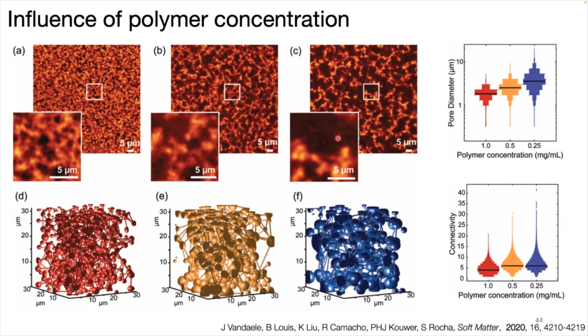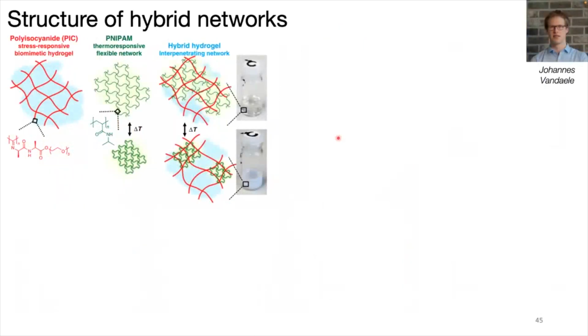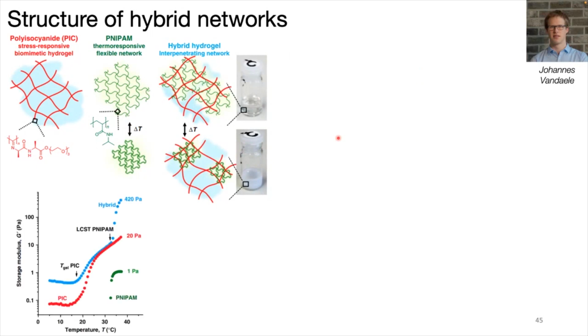Then we are also thinking, okay, we now know how to quantify the structure of this material, but we can take advantage of the fluorescent microscopy to do it in a dynamic way. So we mixed the PIC hydrogels with polyNIPAM. PolyNIPAM is the material that contracts once you warm up, and we were expecting it to change the structure of the hydrogel because the mechanics of the gel changes a lot.